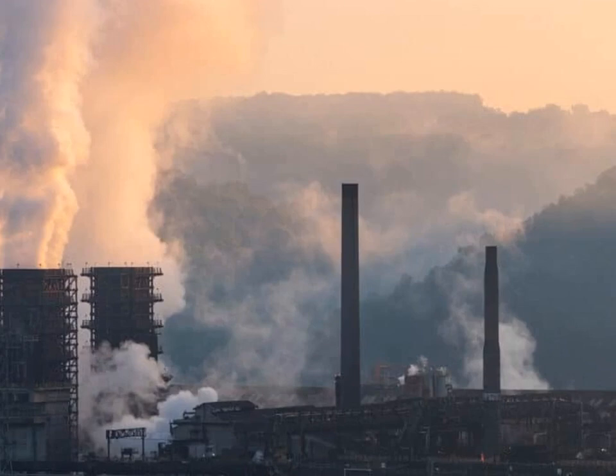The other major SCM studied was granulated blast furnace slag, or GGBFS. That comes from steel making, right? Correct. It's a byproduct of the iron and steel industry. And GGBFS was found to be even more effective in some ways. Replacing 40% of the cement with GGBFS could reduce the concrete's CO2 emissions by about 22%. 22% reduction. That's quite a jump from fly ash. It is. Now, interestingly, the emission factor for GGBFS itself is actually higher than fly ash. It's around 0.143 tons of CO2 per ton.